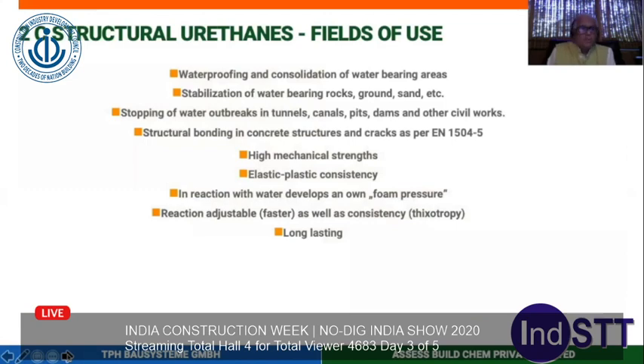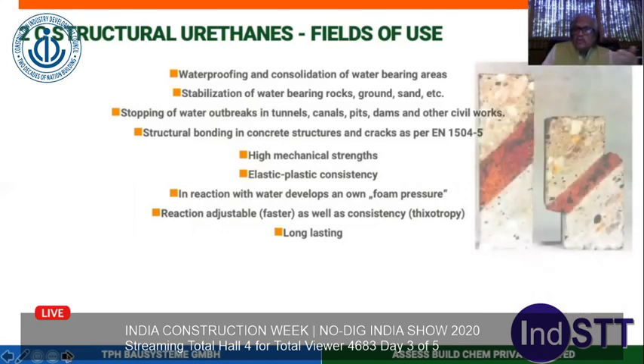And then comes the most important, the two component structural polyurethanes. Structural polyurethanes develop a strength of 70 to 80 Newton per mm square. So you can replace epoxy injections with them, even in cases of dry cracks, so that you don't have to mix too many materials. They can be used underwater. There is no problem of hardening. They are not sensitive to moisture. Their foaming can be controlled from 1 to 15.